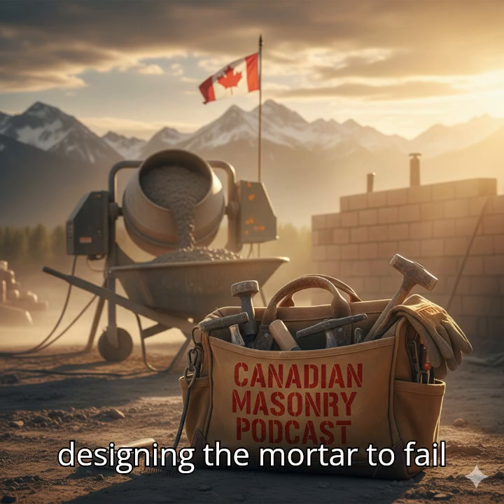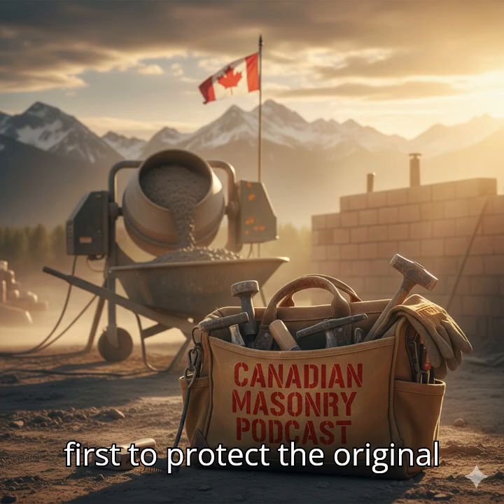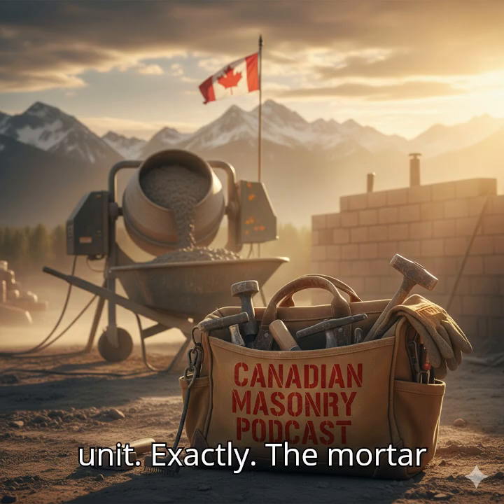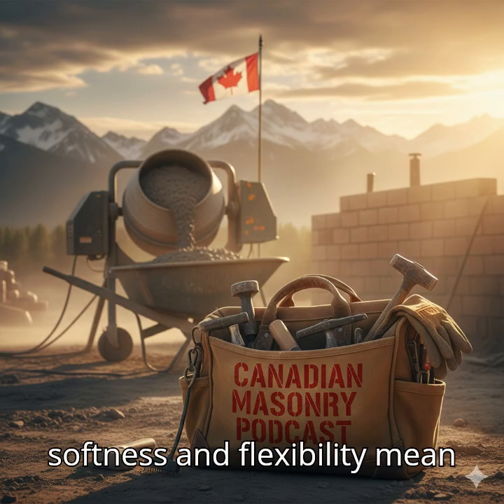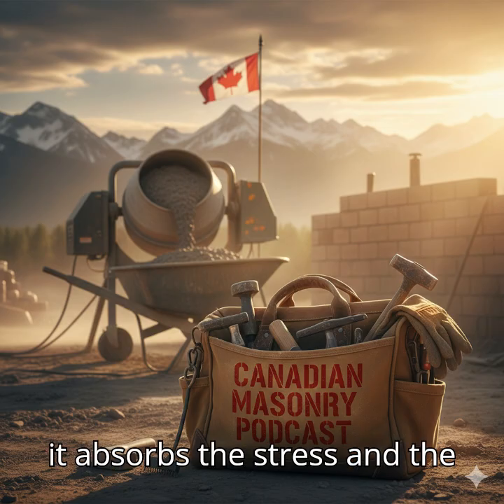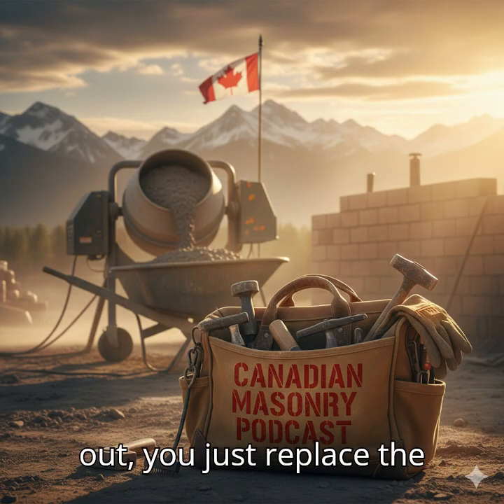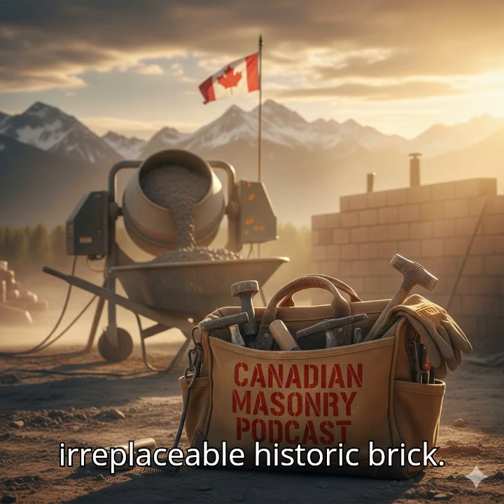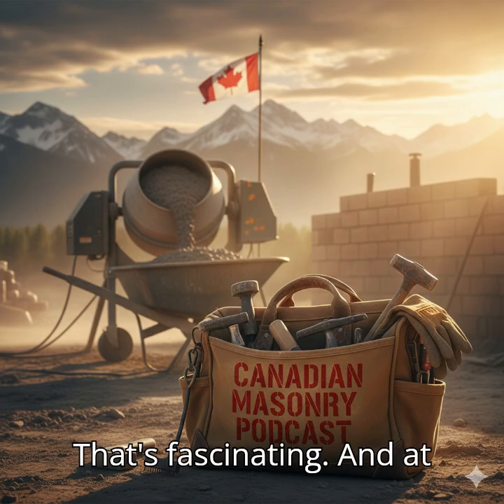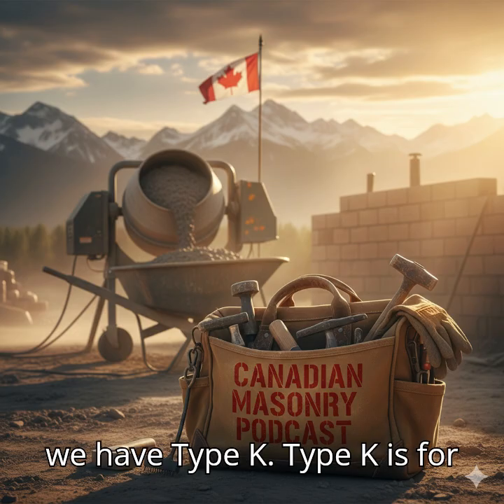So you're intentionally designing the mortar to fail first to protect the original unit. Exactly. The mortar sacrifices itself. Its softness and flexibility mean it absorbs the stress and the weathering. Right. When it wears out, you just replace the mortar, not the priceless, irreplaceable historic brick. That's fascinating. And at the very bottom of the scale, we have Type K.